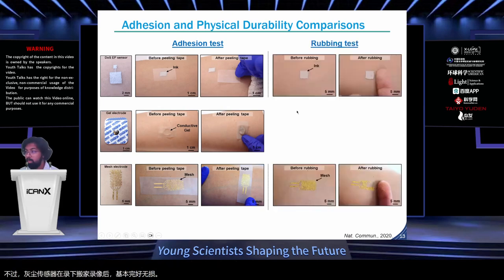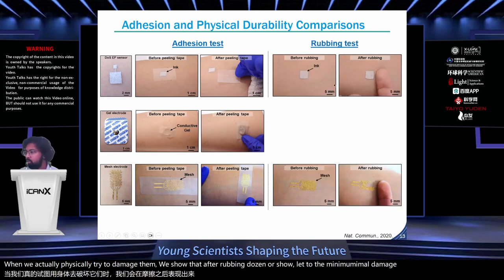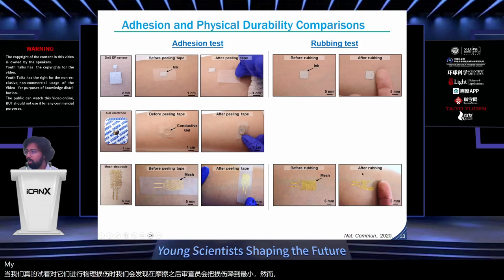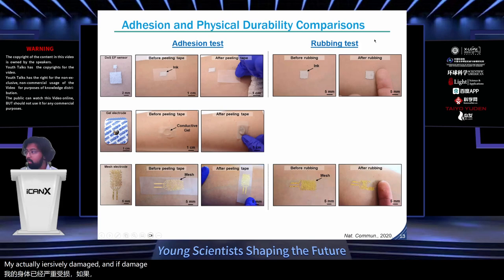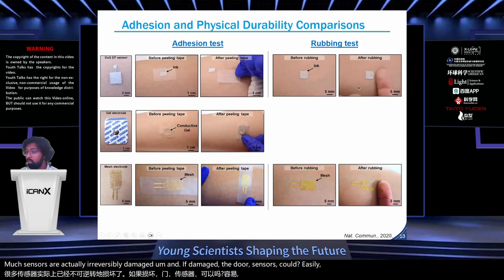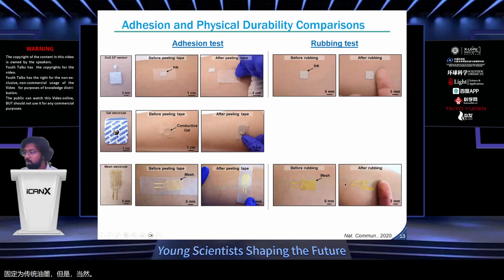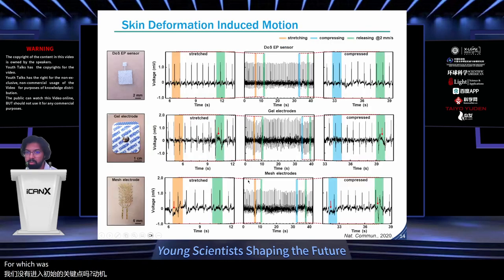When we actually physically try to damage them, we show that after rubbing, DOS sensors show relatively minimal damage, whereas the mesh sensors are actually irreversibly damaged. And if damaged, the DOS sensors could easily be fixed, but of course for mesh, a new mesh electrode would be necessary.